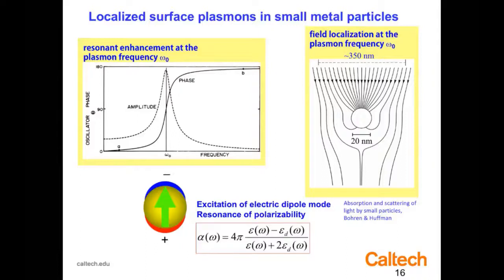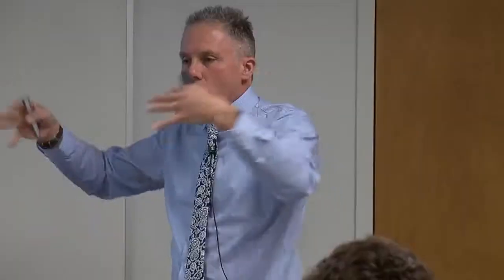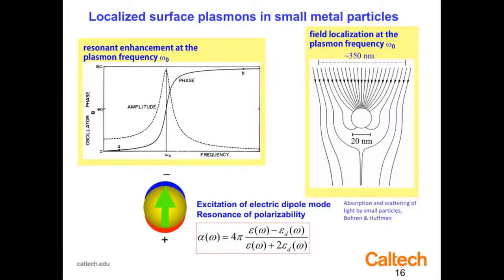At resonance, one of the things that happens with this resonant enhancement of absorption, if you trace the field lines, is that the particle acts like a scavenger or a concentrator for light. Light comes in as a plane wave, and if I look at the Poynting vector map of the light, you can see at resonance that the cross-section of the particle, as expressed by this absorption resonance, is much larger than the physical cross-section. The particle is gathering in light from its surroundings.